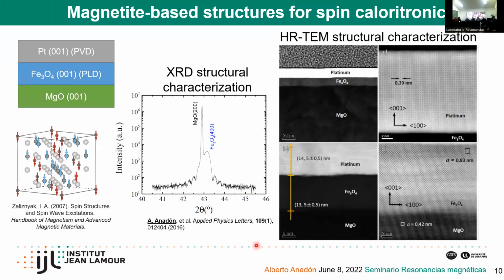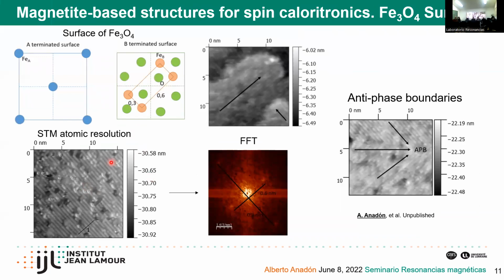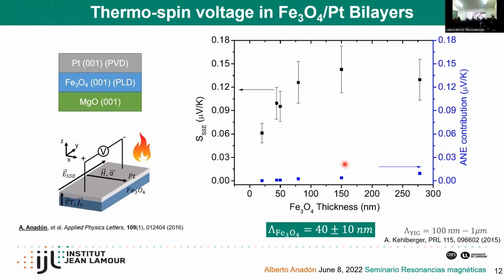So we were also able to characterize the surface of this system using scanning tunneling microscopy. We were able to see atomic resolution in this system, which is quite complicated due to the insulating nature of the magnetite, especially at low temperatures. So we could see the different terraces of the magnetite and the antiphase boundary defects in this system. So basically, from here, the message is we can prepare epitaxial magnetite thin films with very high quality to then take advantage of them to do spin conversion experiments like we did in this system.